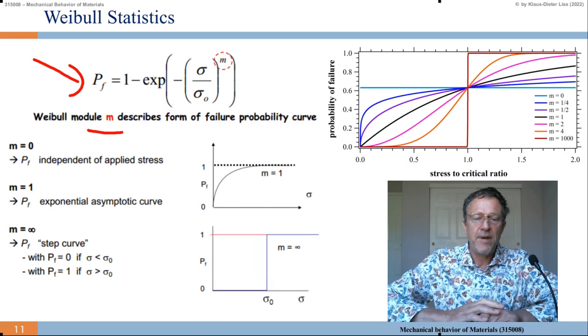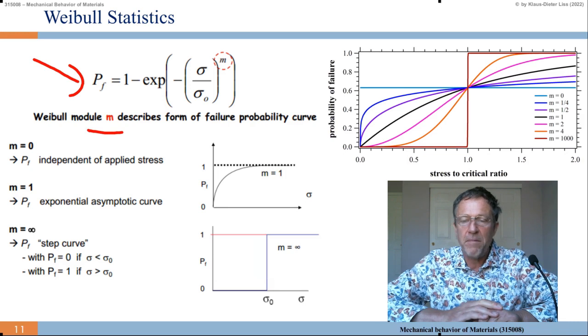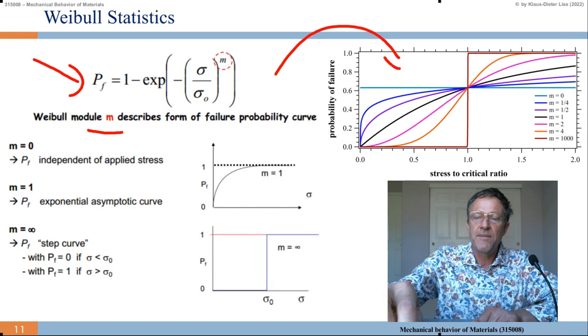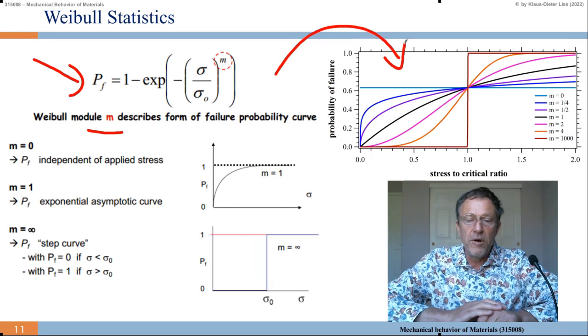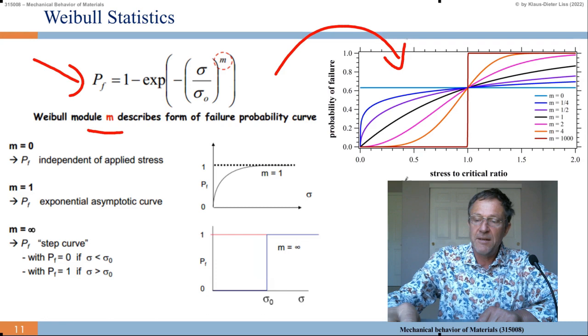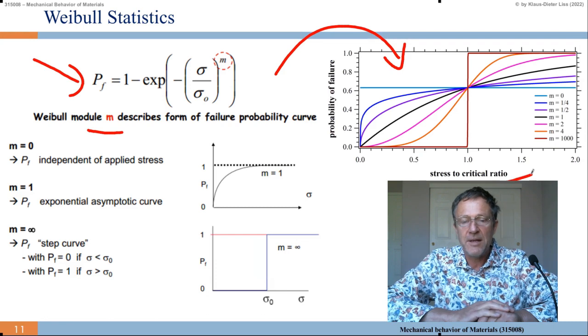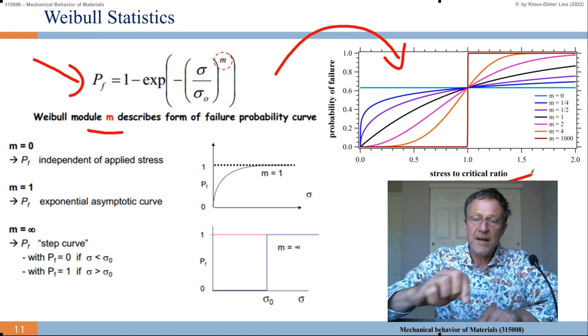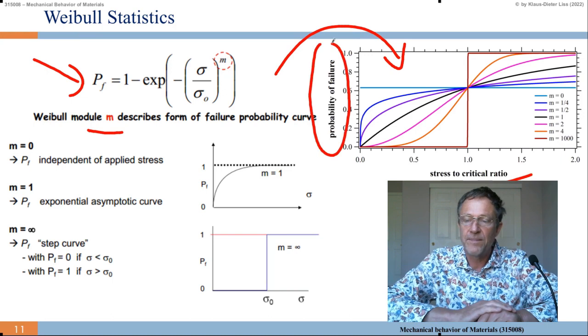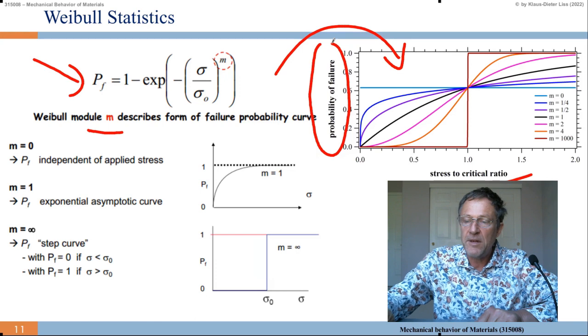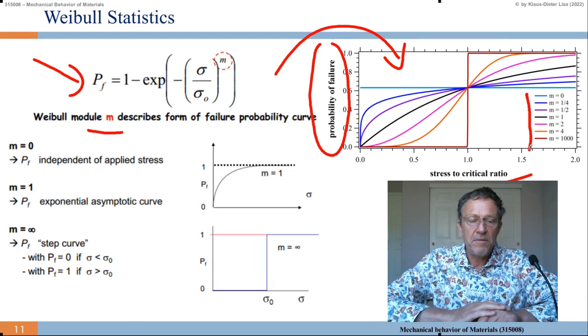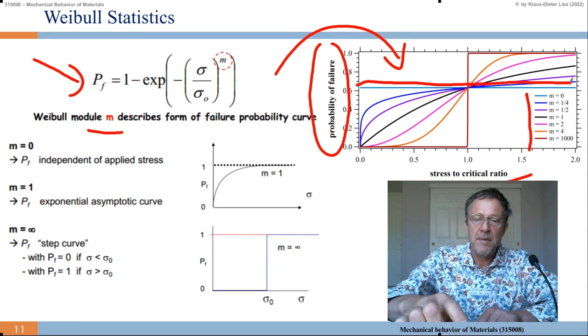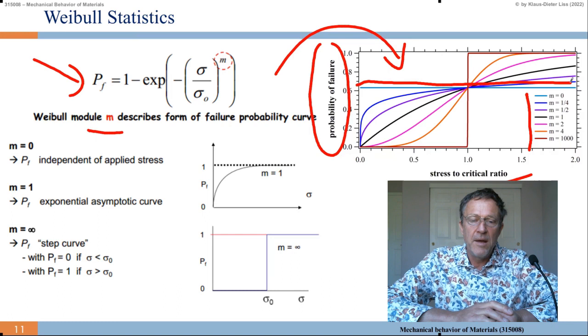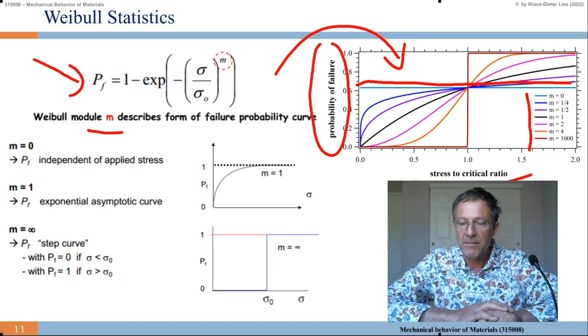I said already we have the Weibull modulus m describing the failure probability curve, and here to the right I have plotted for you a few of those curves with the stress to critical stress ratio, so sigma over sigma 0, and the probability of failure, this PF, for different m. The m's are listed here to the right. And what we see, if m equals 0, then we just get a constant. M equals 0 is e to the minus 1. 1 minus e to the minus 1 is roughly 60%. You can work it out.